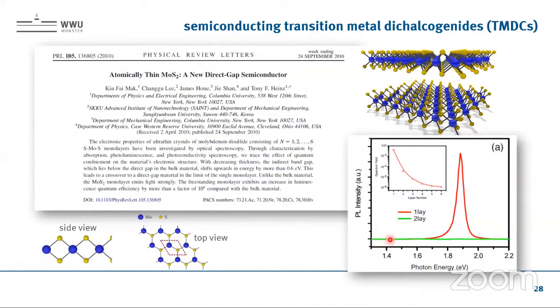If they do it here, it's the energy versus the intensity plotted. For the monolayer in red, you see a strong signal, and on a linear scale the bilayer looks dark. And if they now look at the quantum yields, meaning the intensity as a function of the number of layers, the quantum yield is plotted in a logarithmic representation. And then you see really, the monolayer is bright and then it really goes down dramatically.